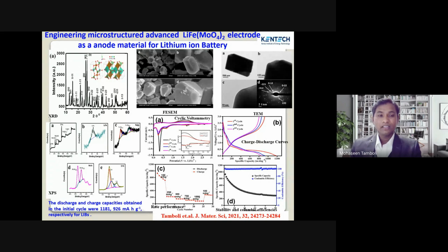So you can see here the XRD pattern of lithium iron molybdate. It shows the same result we observed for sodium iron molybdate. It shows a pure monoclinic phase in XRD. In the SEM data, you can see again the cuboidal-like morphology. After that, we analyzed by TEM. The TEM results are in good agreement with the XRD and the SEM data, showing the cuboidal-like structure. The XPS also shows the same consistent results.